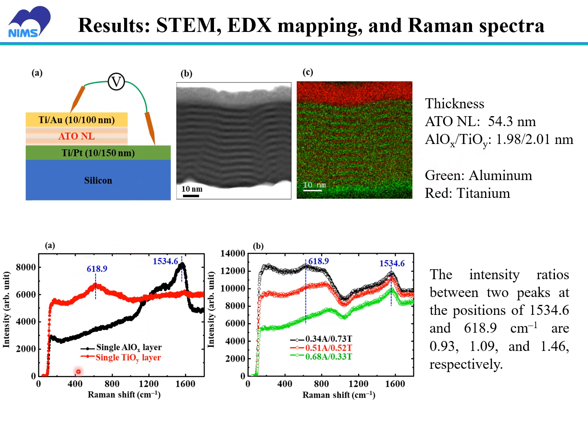This figure shows the Raman spectra for the single ALD aluminum oxide layer and the single titanium oxide layer. We also changed the sublayer thickness for the ATO nanolaminate to measure the Raman spectra. The intensity ratios between the two peaks at the positions of 1534.6 and 618.9 per centimeter are 0.93, 1.09, and 1.46 respectively. With the increase of aluminum oxide content in each sublayer, the shape of the Raman spectra becomes close to that of the single aluminum oxide layer.